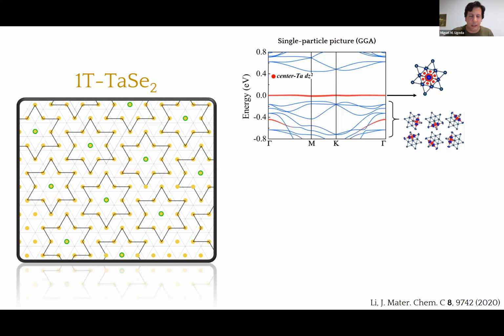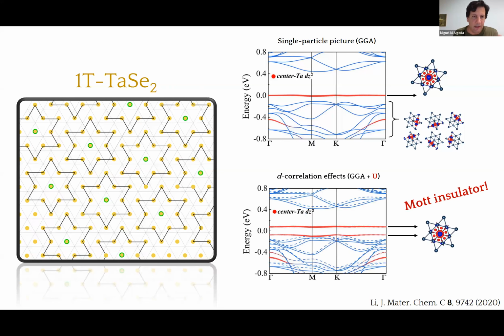So we have one electron localized at the center of the Star of David, holding one half of a magneton, so we can think of it as an array of magnetic moments. And actually, if we now add correlation effects, basically the energy cost to put a second electron at the center of the Star of David, this half-filled band splits into two, right?